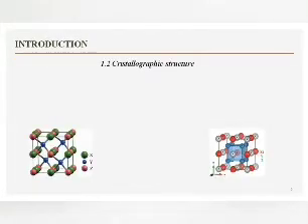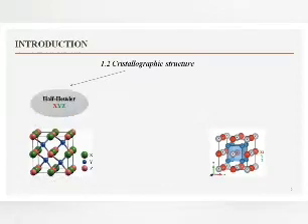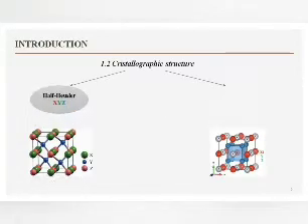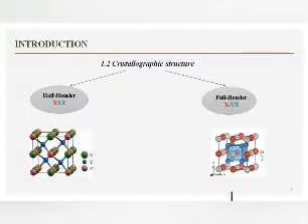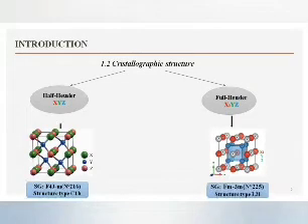Here we present the crystallographic structure of both types of Heusler alloys, half-Heusler XYZ and full-Heusler X2YZ. Half-Heusler materials are crystallized in non-central symmetric C1B structure, having three cubic face-centered sublattices FCC with the space group F-43m, while the full-Heusler is crystallized in structure type L21 with the space group Fm-3m.